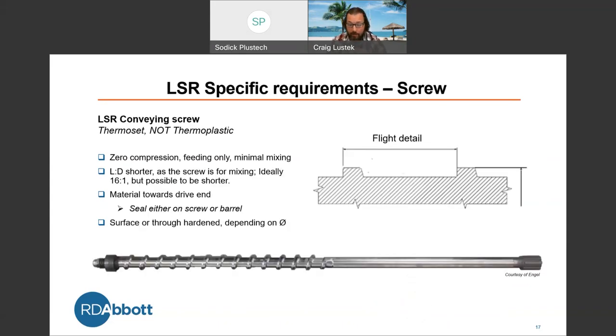Looking at your conveying screw, this is a thermoset, not a thermoplastic. Zero compression, feeding only, very minimal mixing. Your L/D is shorter as the screw is not ideally for mixing. Ideally, we're looking at a 16:1, but we can be shorter in that ratio. Again, material towards the end drive. The seal can either be on the screw itself or on the barrel assembly, depending on the setup. And the screw can be surface hardened or through hardened, depending on that diameter.